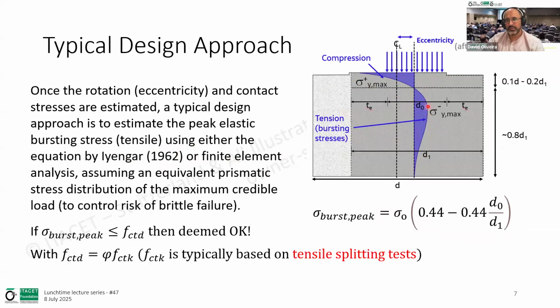It's not the average. We look at the peak tensile stress here at a maximum credible load, because we are concerned that this could cause a brittle failure. So we look at this maximum value here, and we compare to the tensile capacity, the design capacity of the concrete, which is the tensile characteristic strength divided by a reduction factor, which is typically estimated or tested under tensile splitting tests, or the so-called Brazilian tests.